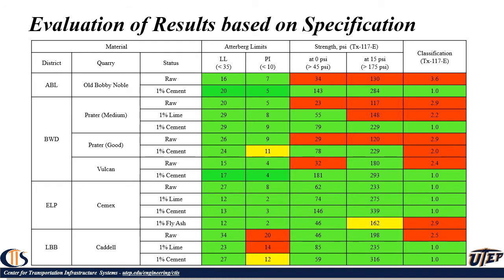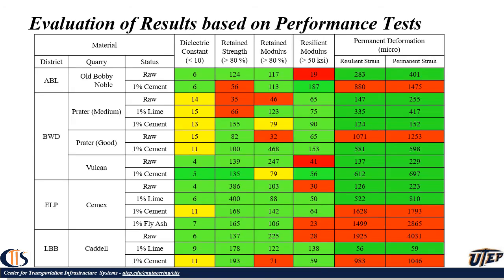The same thing for a different material. You see that for the second material, the lime was not effective, but the cement was. And all you see common is we are not using more than 1%. And you see that in the majority of the materials, we could engineer with 1% additives to pass all the requirements of the specification and be a grade 1. It means a high quality base.